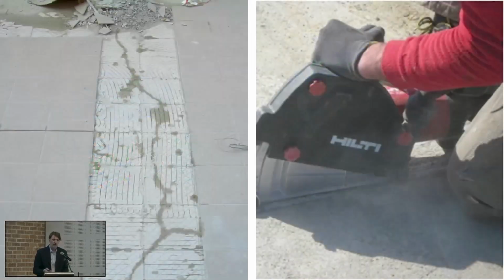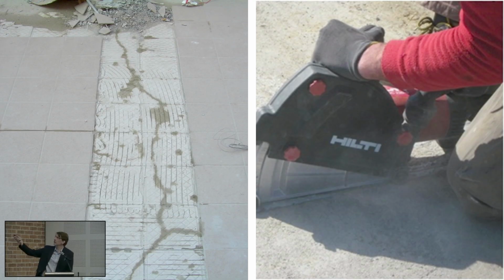Maybe you have cracks because you don't do the joints. Cement needs expansion joints, every 9 square meters, 25 square meters, 12 square meters, depending on the application you have to do. But we have to do that. We have to cut it 1/3 of the thickness of the screed, of the substrate, and then do the joint. Otherwise, we have a crack like this.